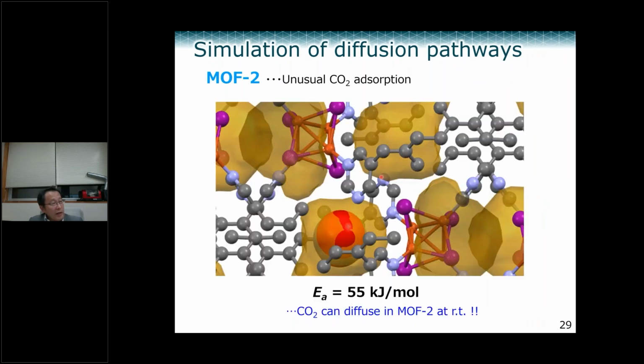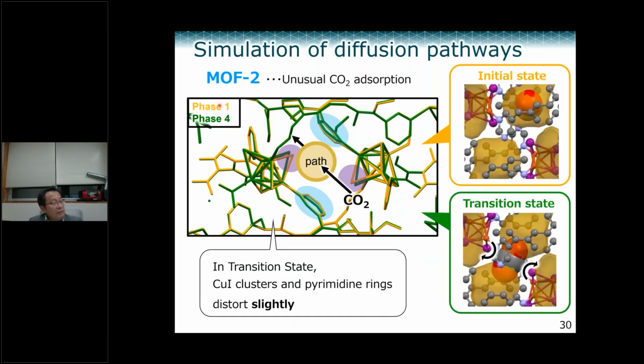The next slide shows the structural difference between the initial position, phase 1, and the transition state, phase 4. As you can see, there is a small difference, slightly shifted, but not like MOF1. Just a slight structural change allows the CO₂ to move to the next point. The biggest change is this connector part. This copper cubane unit is this one. This bridging iodide is slightly shifted this way, so this void widens. And this pyrimidine group is also pushed out a little bit like this. However, a relatively small structural change occurs.